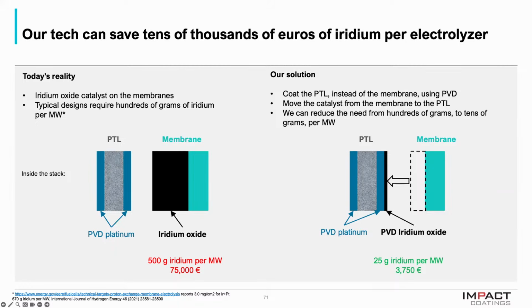So is there anything we can do about this? Yes, there is. We can actually coat the porous transport layer with iridium oxide instead of having the membrane coated. And this we do by PVD. You can think of it like we're moving the catalyst functionality from the membrane onto the PTL. By doing this, we can reduce the need for iridium from hundreds of grams to tens of grams per megawatt. Some numbers to that, you can see on the slide here, it says 3,750 euro. So we're talking about an order of magnitude in cost saving. And this, of course, has tremendous value to our customers.